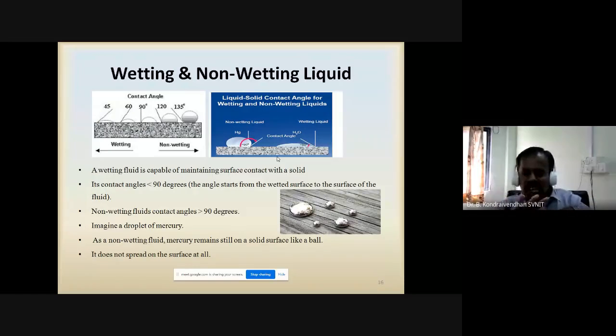So now you can differentiate what is a wetting liquid and what is a non-wetting liquid. If your contact angle is less than 90, it is a wetting liquid. If your contact angle is more than 90, it is a non-wetting liquid. So mercury is a non-wetting liquid. Even though it is on the surface of the plank, it does not go inside the cracks unless you apply some external pressure or force. It remains on the surface, keeps its shape, and does not spread on the surface at all.